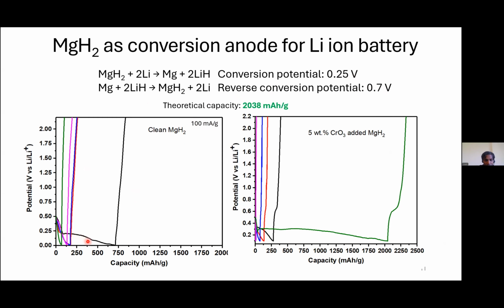And that sample, when you are using it as an anode active material in a lithium-ion battery, provides a capacity of just around 700 milliampere-hours per gram, which is very, very less, right? Almost only 1/3 of the capacity. And what about the reverse conversion? You need to have the conversion at 0.7 volt or so. And no, the curve is going to heaven. There are no changes, and the further cycles also decrease, and there is no reverse conversion at all.